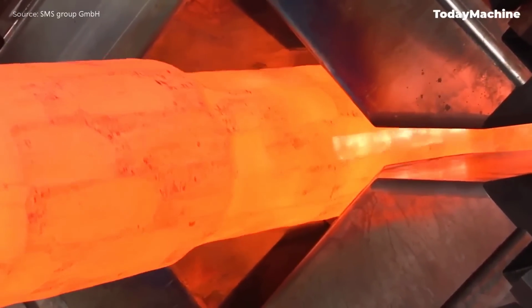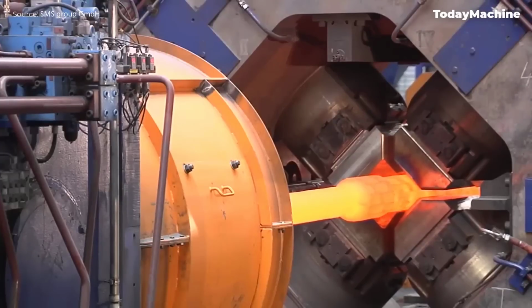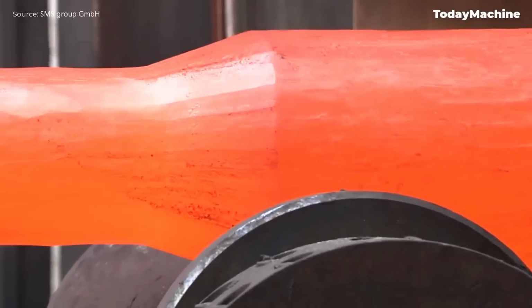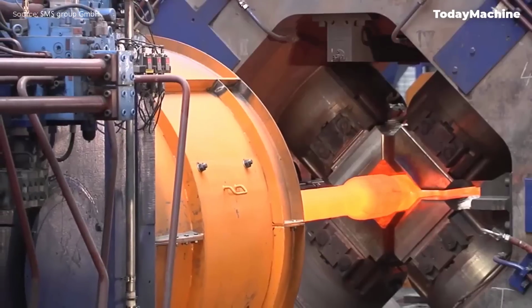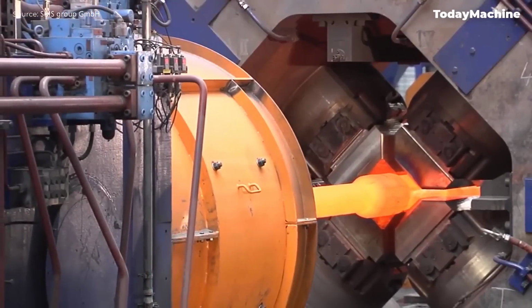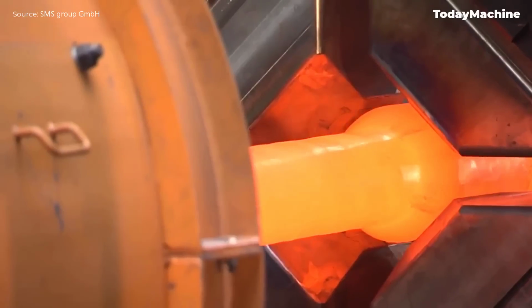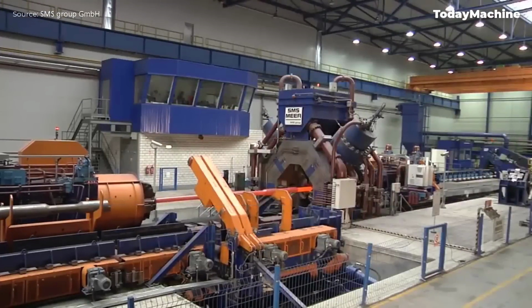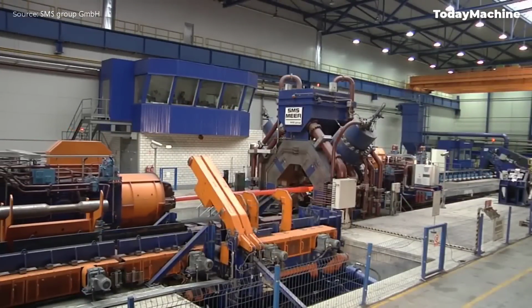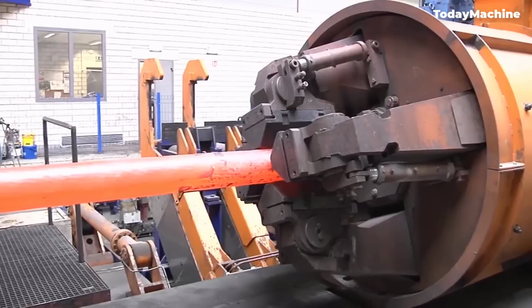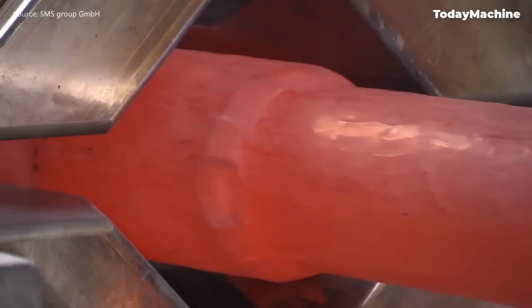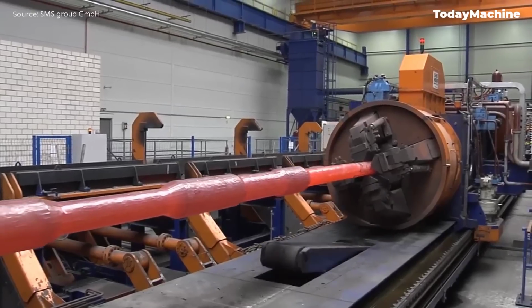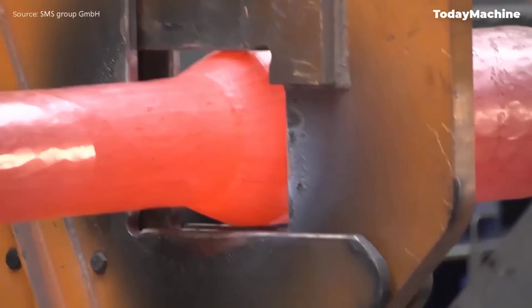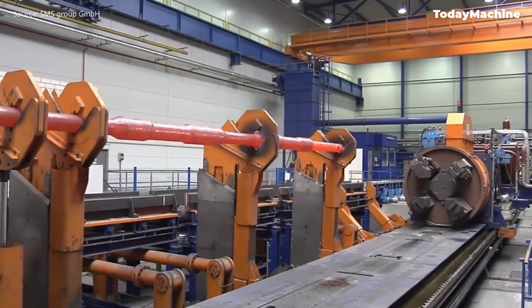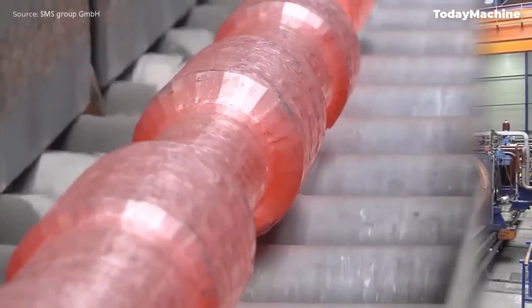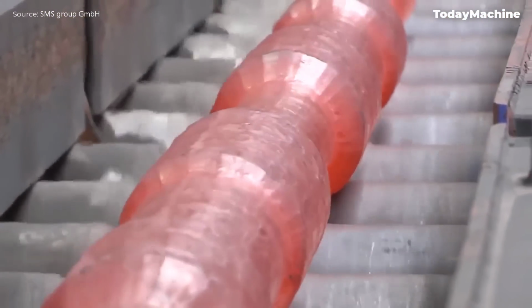The SMX-type machines are versatile, capable of forging round, square, and octagonal long products, as well as flat products with varying edge profiles. They can even forge thick-walled seamless tubes with minimal wall thicknesses over a mandrel. The innovative press cylinders allow for up to 240 strokes per minute, depending on the machine size, ensuring high productivity, precision, and surface quality. The near-net shape production minimizes the need for extensive machining, resulting in high-quality, energy-efficient workpieces with a high material yield.